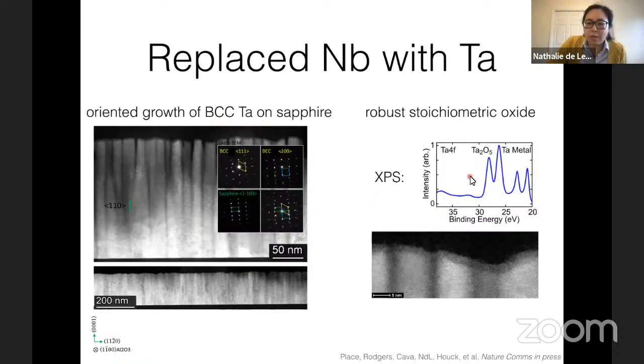And then what we see in these films is basically a 2 nanometer thick oxide everywhere we look that does not care what you do to it. You can throw it in acid, you can throw it in base, you can heat it up, and you always have this 2 nanometer thick oxide. And it's very robust and stoichiometric. So you always see Ta2O5, in contrast to niobium, where you just look at it funny and it turns into a new stoichiometry.